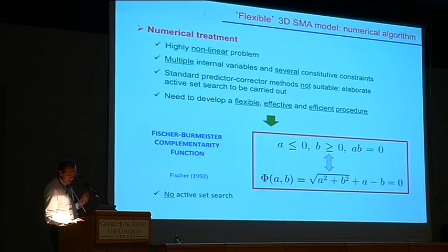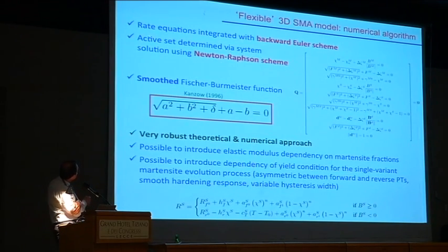But my feeling is that since the model was really thermodynamically consistent and well designed in a continuum and mathematical framework, all these manipulations lead to a very robust numerical scheme. So the thing we did, we integrate the rate equations again with the backward Euler scheme. We end up with a huge number of equations now, and we decide to solve this highly nonlinear system with a Newton-Raphson scheme, and to make the system automatically on its own decide what is really the active phase transformation, if there is only one active phase transformation, or maybe two active phase transformations, and so on.